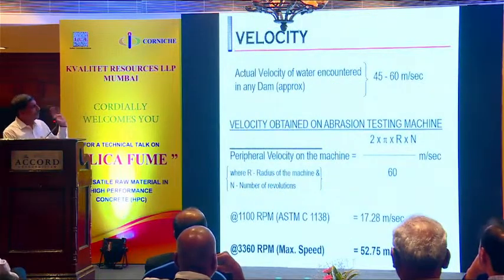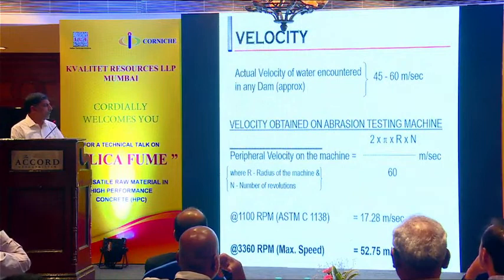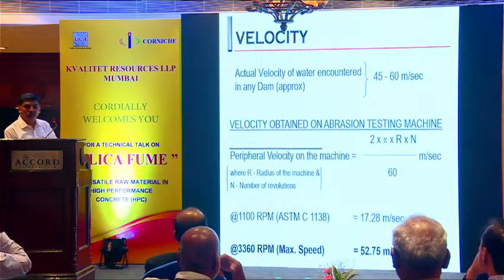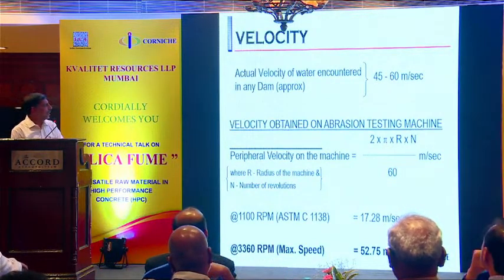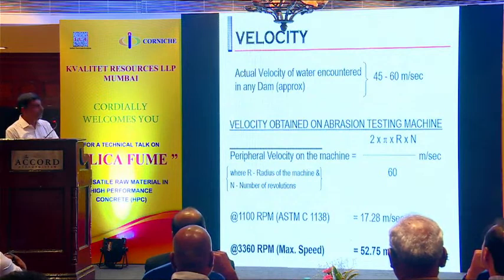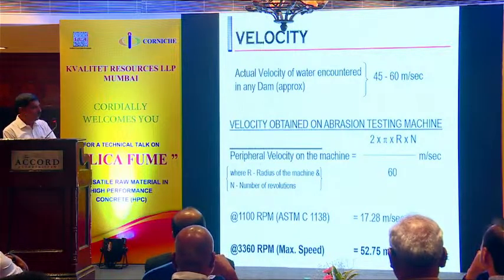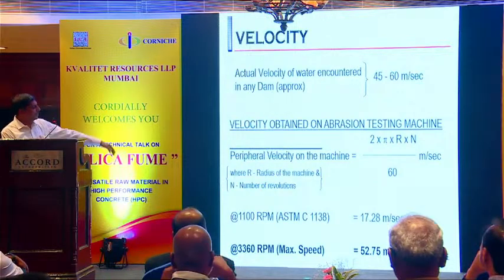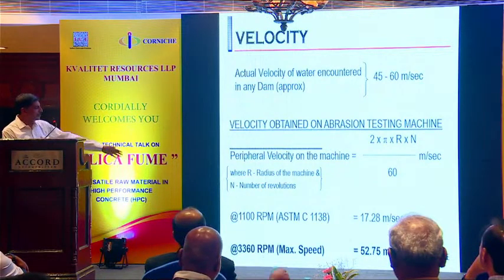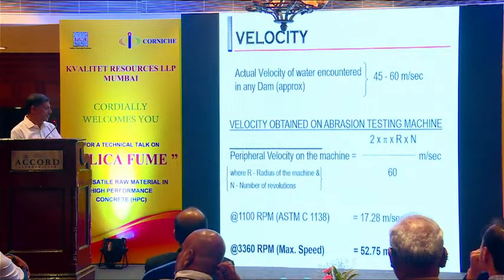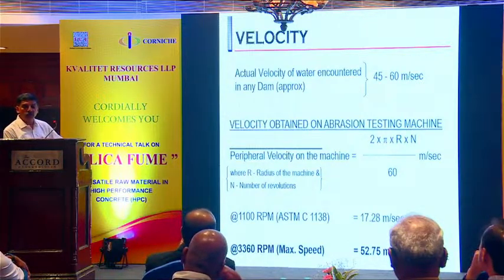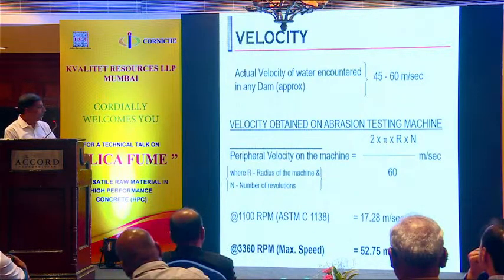The only change we made was the RPM. What is recommended as per ASTM is 1100 RPM. And we were given to understand the velocities of water encountered in any dam here is approximately 45 to 60 meters per second. Working backward, with 1100 RPM, it was way, way too slow. It was giving us maybe 18 to 20 meters per second. So we increased the speed by 3 times. All the tests we have done in India are at 3,360 RPM, to simulate and come closer to real life.